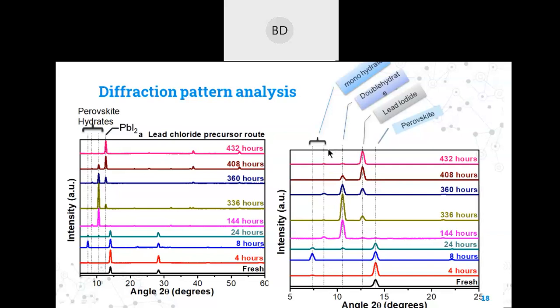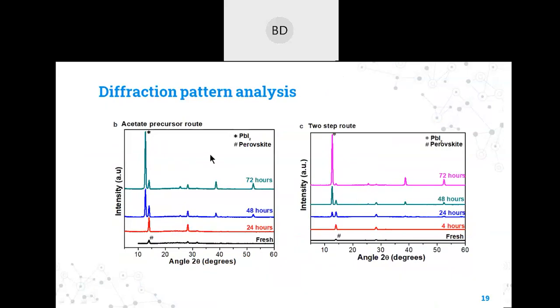So if you see here, there has been some other form of perovskite which is forming when you are keeping this perovskite under humidity exposure. But the same is not happening with other two routes. Here, the perovskite, after a long time of aging, is degrading directly into the lead iodide, which is one of its constituting elements. And in the two-step route also, it is directly degrading into the lead iodide. We didn't observe any signature of perovskite hydration formation in acetate precursor route and two-step precursor routes.